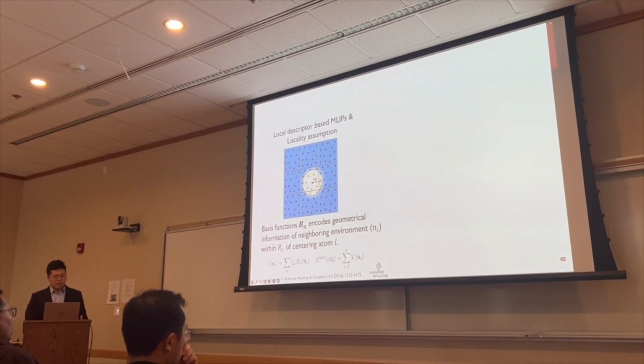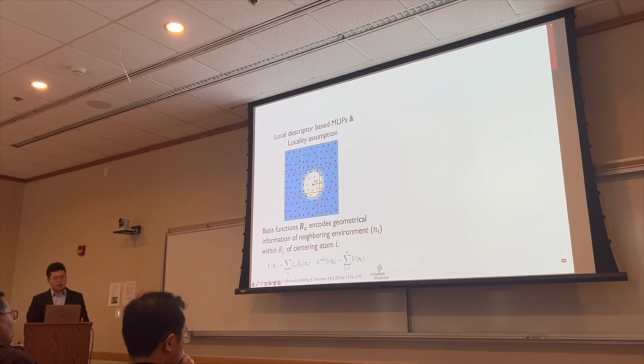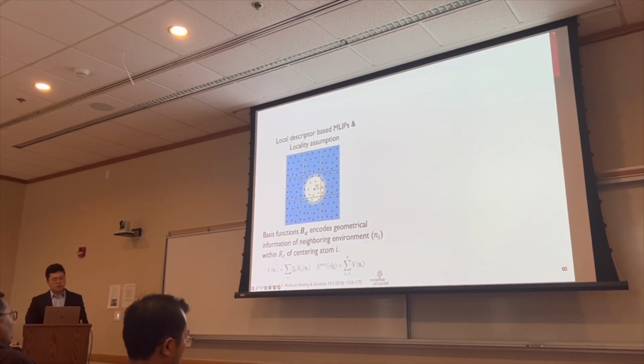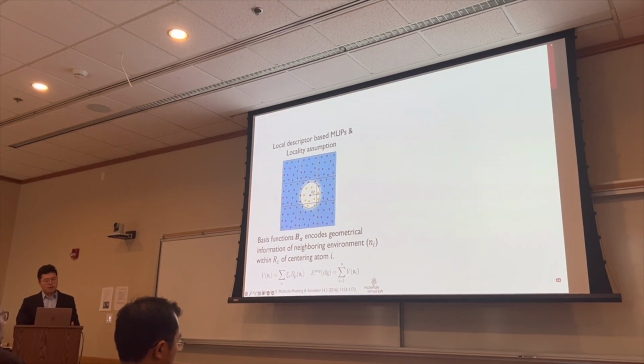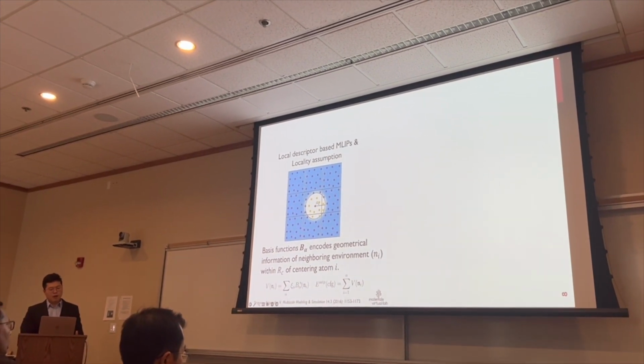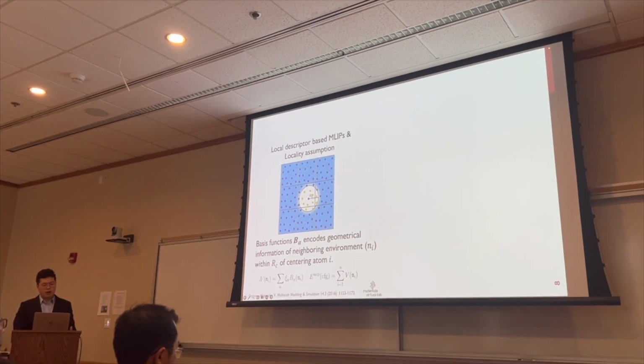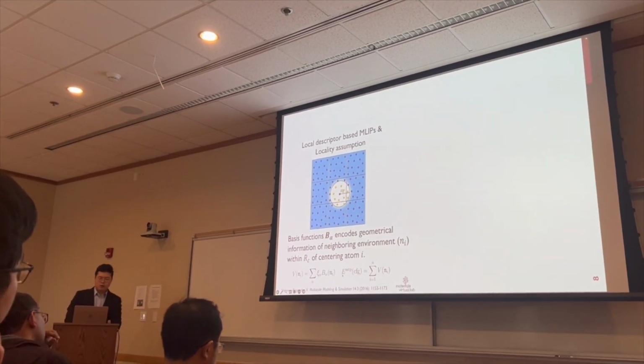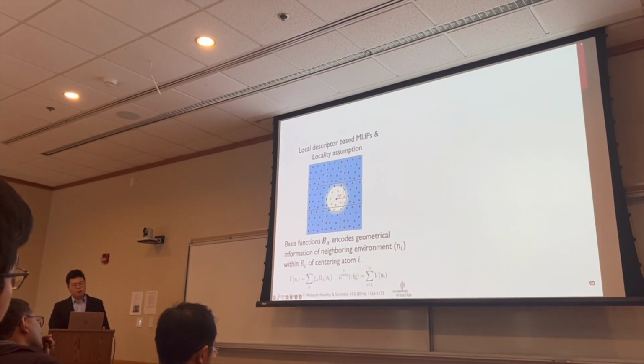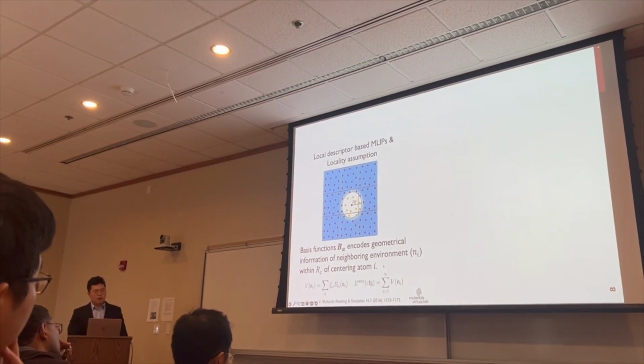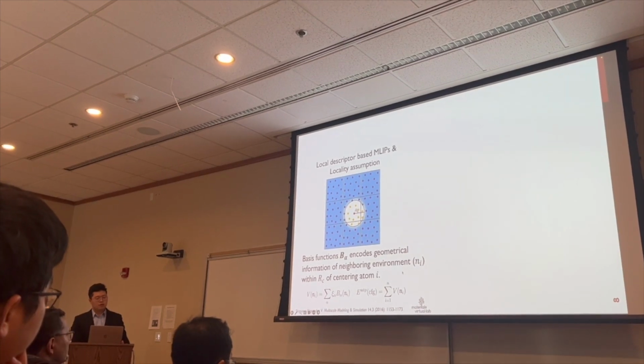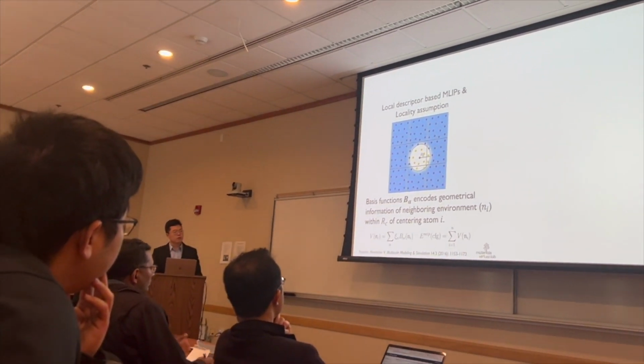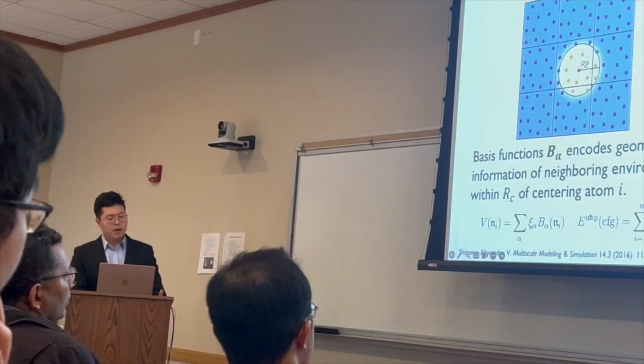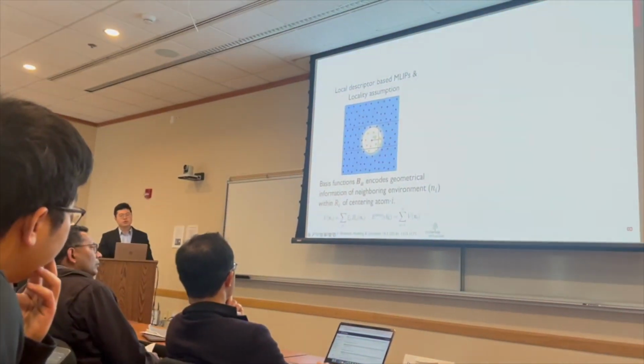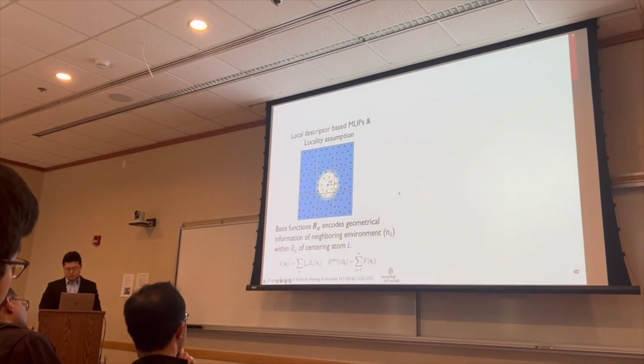And with this B alpha, we can use this equation to express the atomic energy. So here is some trainable coefficient, and it is multiplied with the B alpha, whose summation equals the atomic energy. And the summation of the atomic energies represents the total energy predicted by the machine learning interatomic potential. And with some machine learning algorithms like linear regression or artificial neural networks, we can fit those trainable parameters so that the total energy predicted by the machine learning potential matches the ground truth, which is usually DFT results.